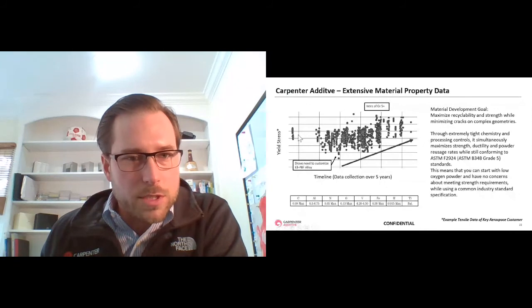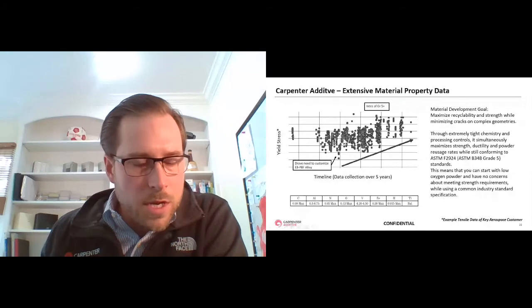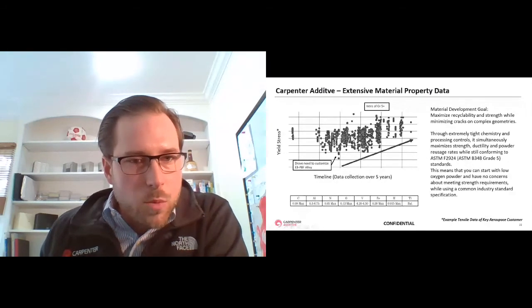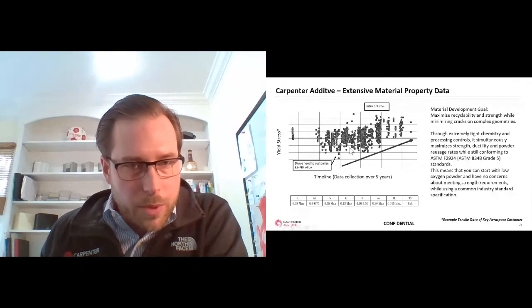We've had to anonymize the data. But what we're seeing here is in the early days, using a broader spec for our titanium 6-4 powder, we had quite a large scatter of our results of AM printed parts, right? Then what you can see is that as we iterated and put process controls in place, we started to reduce some of the number of outliers that we saw, right?